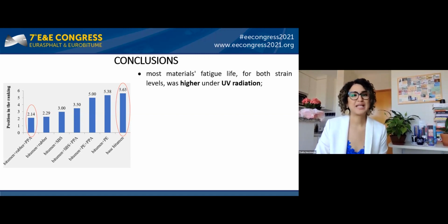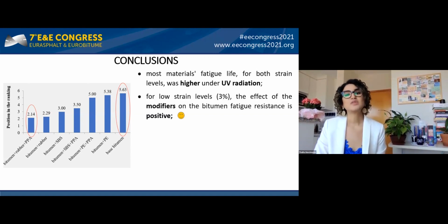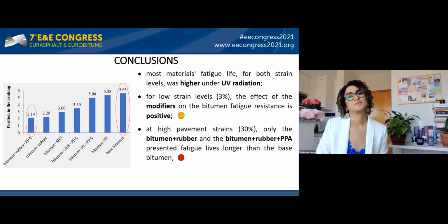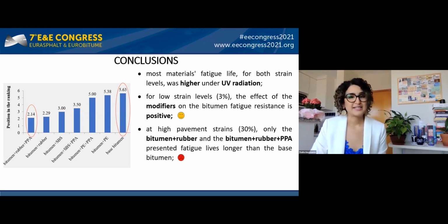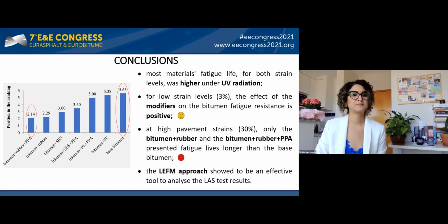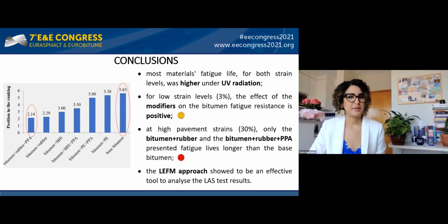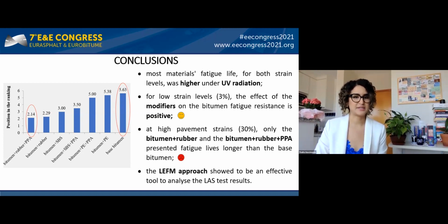And to conclude, I can highlight that most materials' fatigue life for both strain levels was higher on the UV radiation. For low strain levels of 3%, the effect of modifiers on the bitumen fatigue resistance is positive for all aging levels. At high pavement strains, 30%, only the bitumen plus rubber and rubber plus PPA presented fatigue lives longer than the base bitumen. And the LEFM approach showed to be an effective tool to analyze the LAS test results.